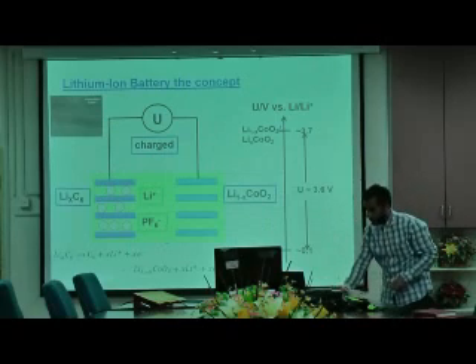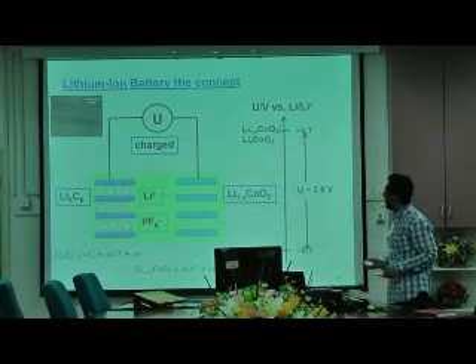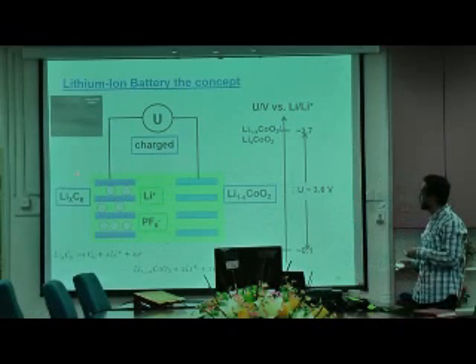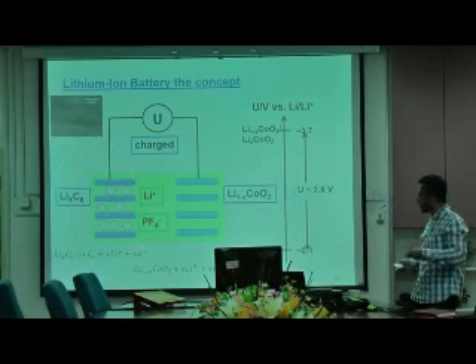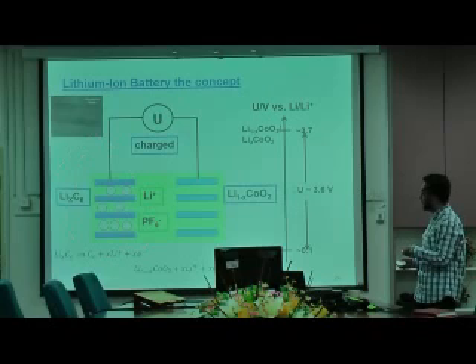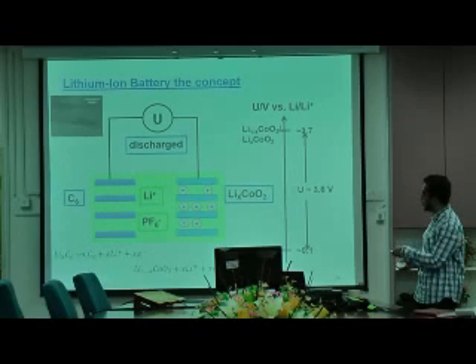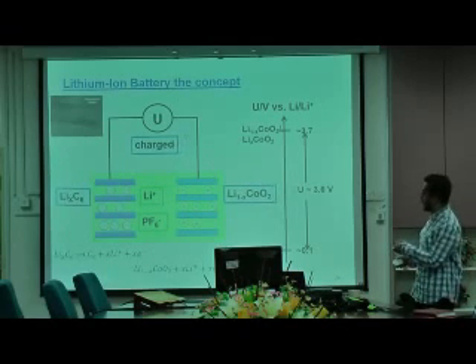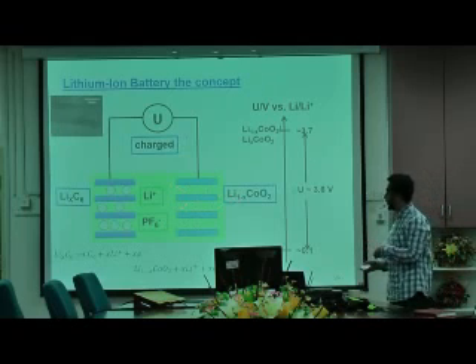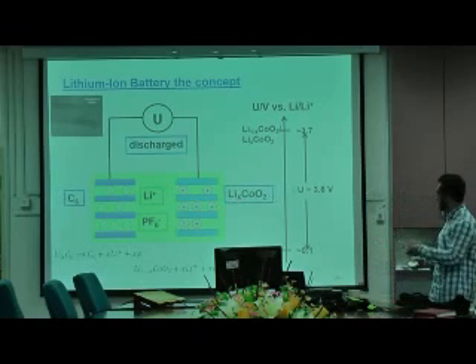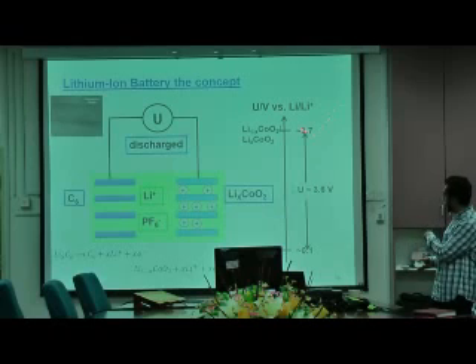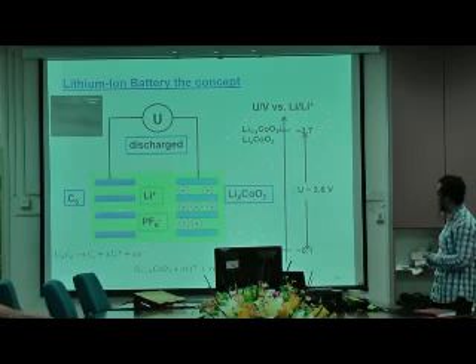This is a brief description of how lithium ion works. Lithium ion normally uses graphite. The commercial establishment uses a graphite anode, where the lithium intercalates between the cathode and the anode. During discharge, the lithium moves from the anode to the cathode, and during charge, vice versa. The potential difference between the redox couple of lithium going into the graphite and lithium going into, in this case, cobalt oxide is about 3.6 volts.